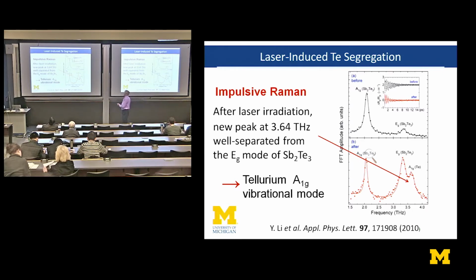This had actually been reported just previous to our work, but it had, fortunately, been reported as an incorrect result. It had been reported as an optical phonon excitation of the intact structure, antimony telluride, because its position here is close to that of an Eg optical phonon. But there's a small difference, as you can see here, between this new peak and the Eg mode, and that difference is crucial in interpreting this peak correctly. And what it showed was that we can actually use the laser field to modify the interatomic potential.